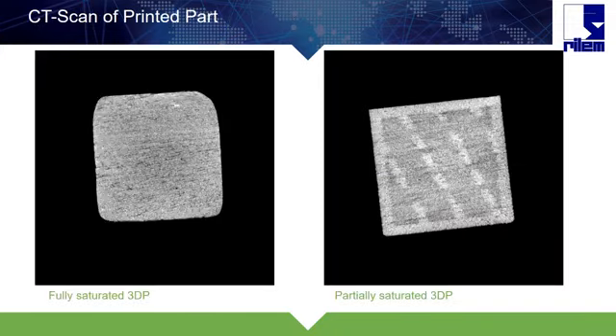At the end, I want to show you the CT scan of the printed materials and how we can clearly see the inside of the materials and the saturation level of each specimen. On the left, you can see the fully saturated 3D printed material, and on the right you can see the partially saturated 3D printing. The partial one does not put the liquid on the entire specimen, whereas the fully saturated ones are fully saturated with the liquid material.